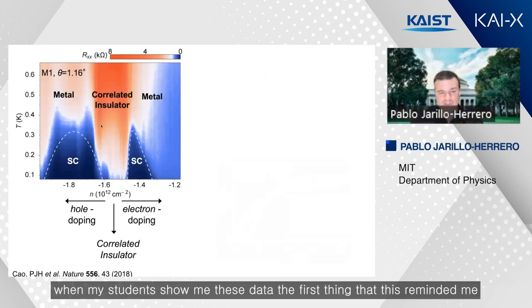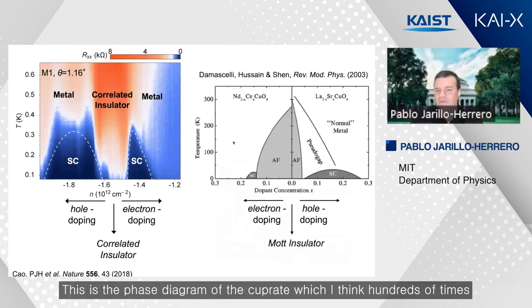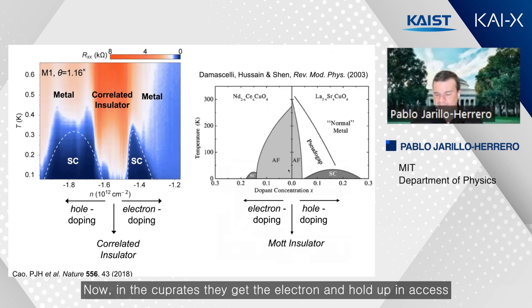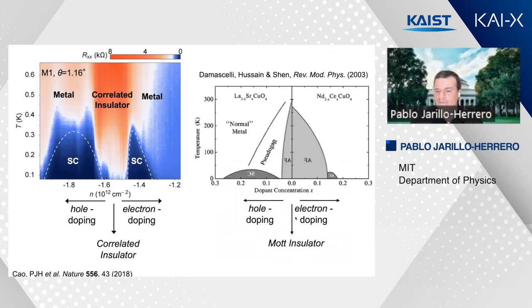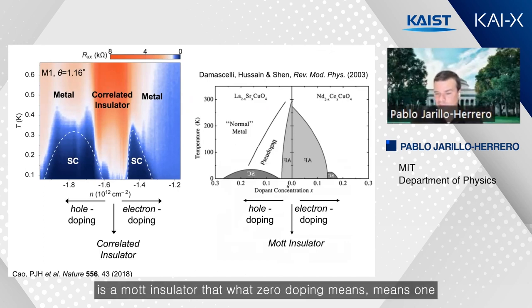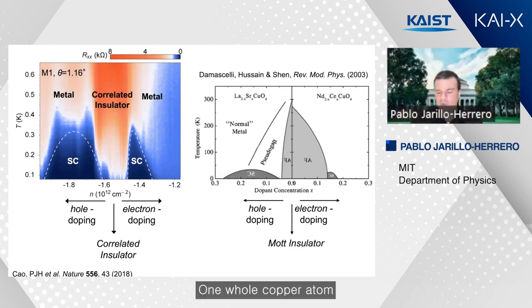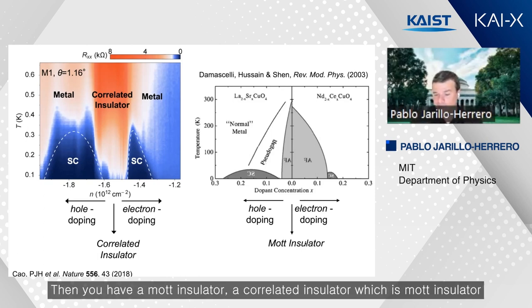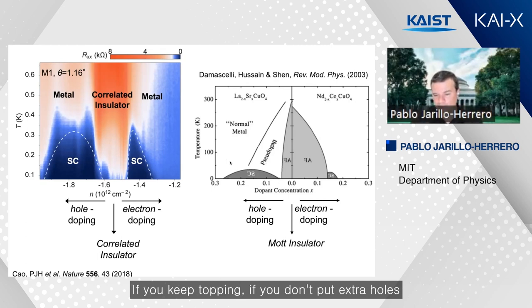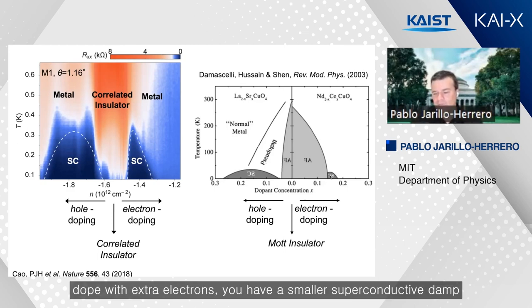Now, when my students showed me this data, the first thing that this reminded me of is phase diagrams such as this. This is the phase diagram of the cuprates, which I've seen hundreds of times. Now, in the cuprates, they get the electron and hole doping axis opposite to what I showed here, so let me flip them for you. So in the cuprates, a doping of one hole per copper atom is a Mott insulator. That's what zero doping means, relative, one hole per copper atom. So then you have a Mott insulator, a correlated insulator state. If you keep doping with extra holes, you have a superconducting dome. If you dope with extra electrons, you have a smaller superconducting dome.